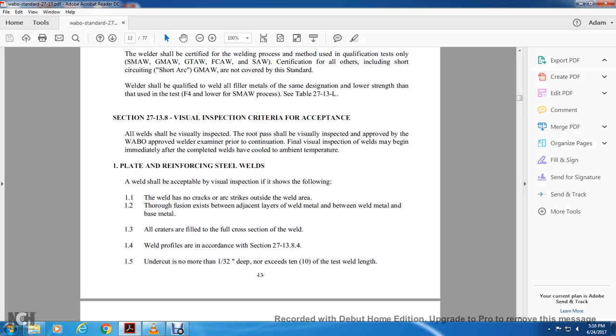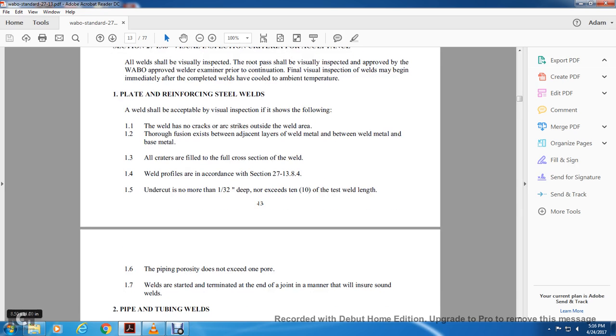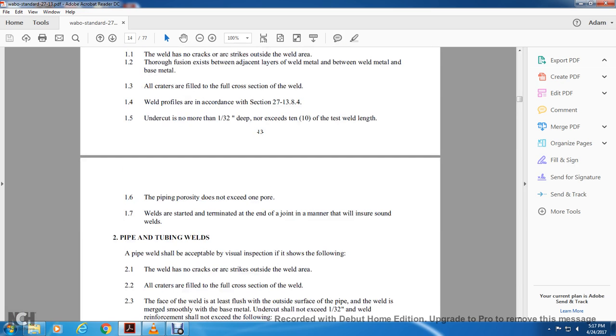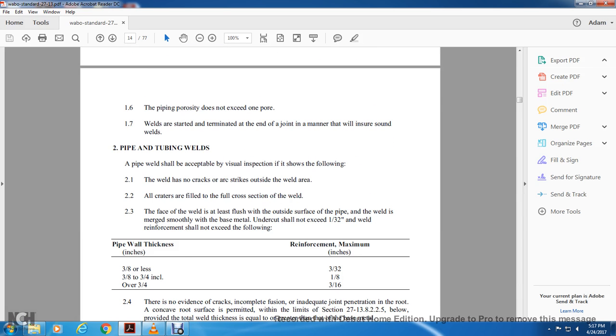Undercut is no more than 1/32 of an inch deep nor exceeds 10 percent of the test weld length. The piping porosity does not exceed 1 pore. Welds are terminated at the end of the joint in a manner that will ensure sound welds. Piping and tubing. All pipe welds should be accepted by visual inspection showing the following.